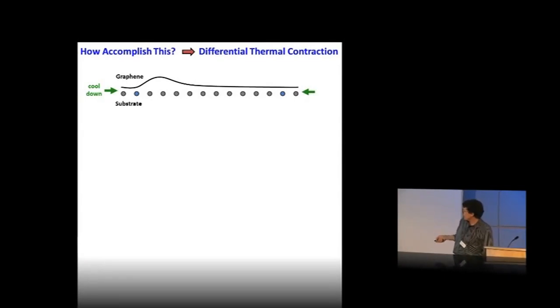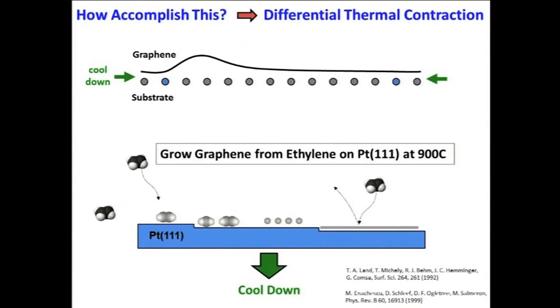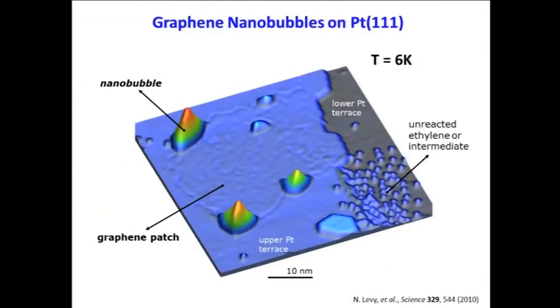So we tried out this idea by epitaxially growing graphene on platinum at high temperature. And then we cooled down the graphene and looked at it with our STM. I just want to mention that other people have grown graphene on platinum long before us, and so we copied their recipes, for example, Comsa's group and Salmeron's group. So we just copied their recipes and grew it, and then we looked at it at low temperature, and we saw something kind of interesting.